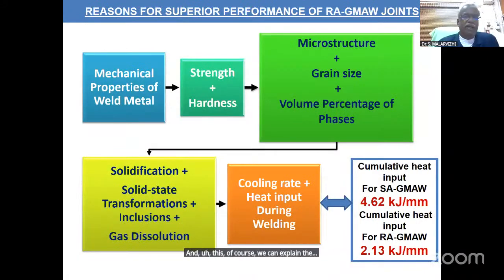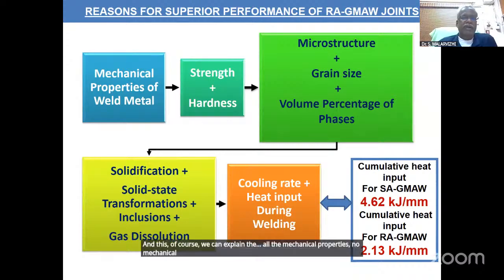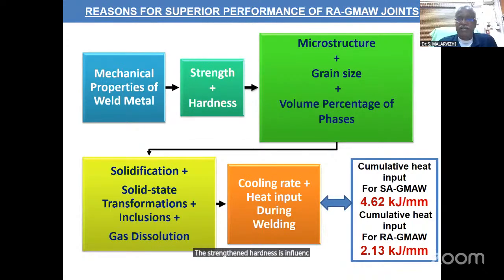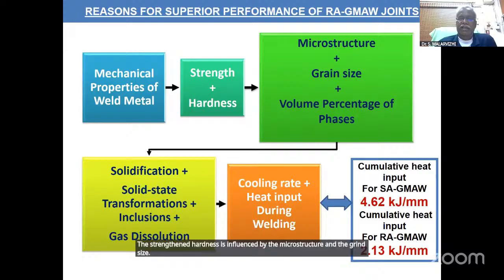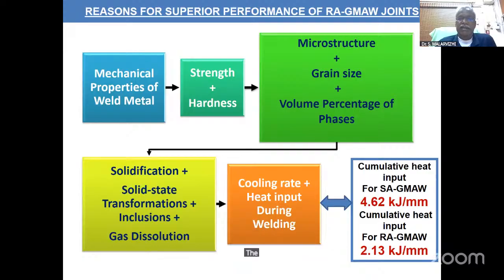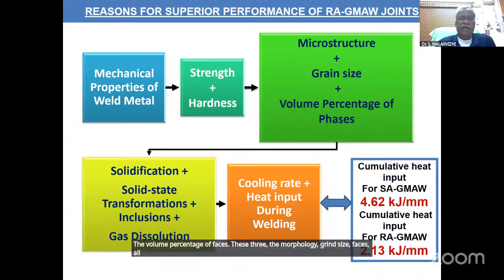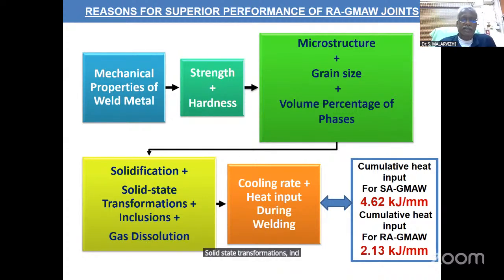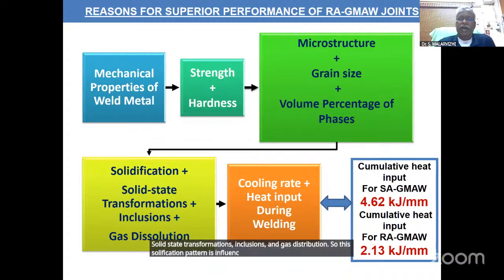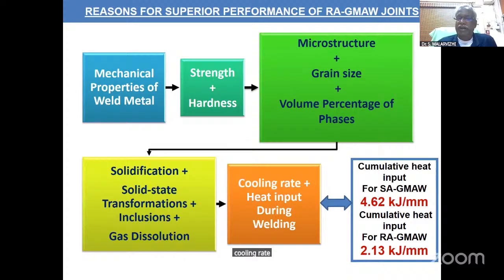All the mechanical properties of the joints, of the weld metal, are nothing but strength and hardness. The strength and hardness are influenced by the microstructure, the grain size, and the volume percentage of phases. These three, the morphology, grain size, and phases, are all influenced by the solidification pattern, solid state transformations, inclusions, and gas distribution. So this solidification pattern is influenced by the cooling rate and heat input during the welding process.